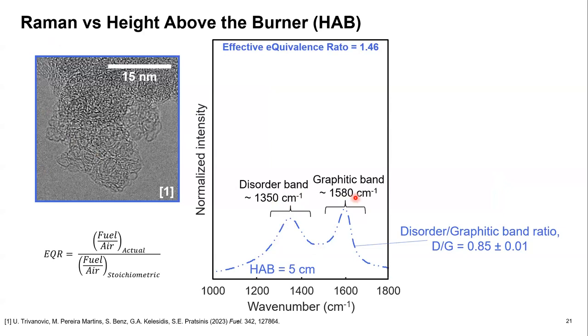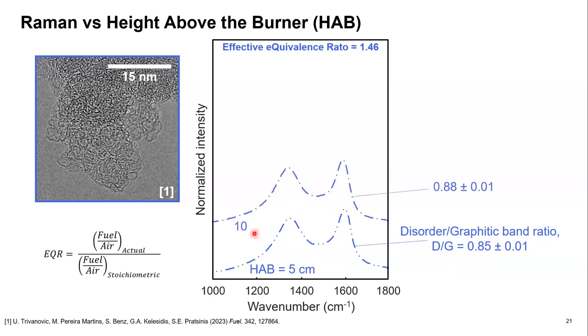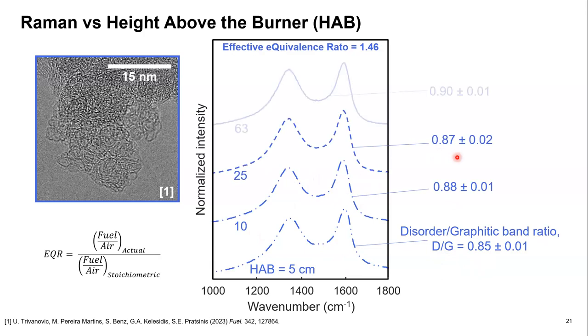In order to try to quantify the amount of order or disorder within the particles, we can take the ratio of the peak intensities and understand something about how the relative amount of order or disorder compares. So here at the leanest equivalence ratio, at the smallest height above the burner, 5 centimeters, we had a D to G ratio of 0.85. Moving up to 10 centimeters above the burner, this increased slightly to 0.88. At 25 centimeters, this was 0.87. And at the exit, it was 0.9.